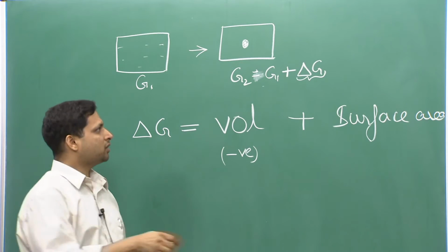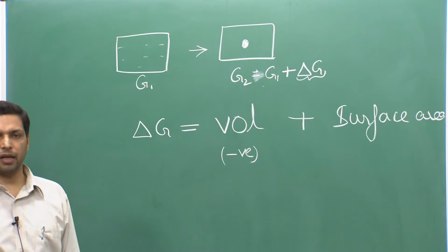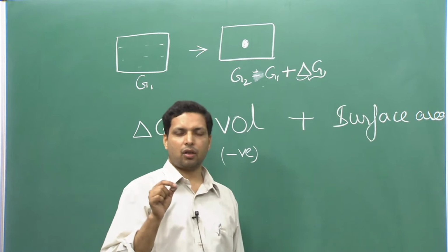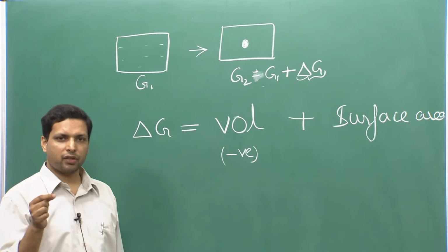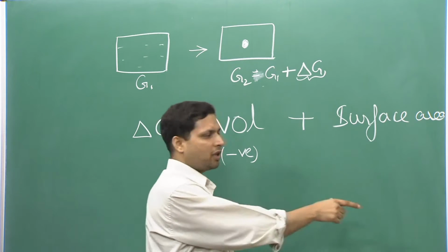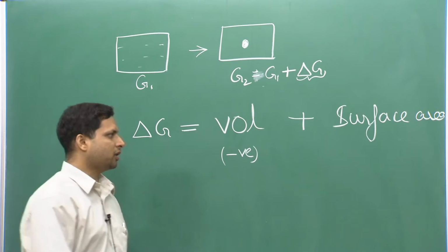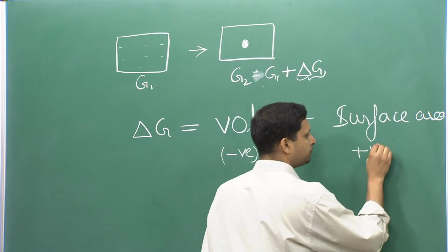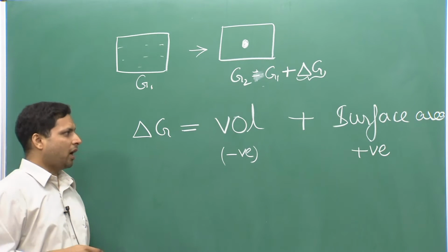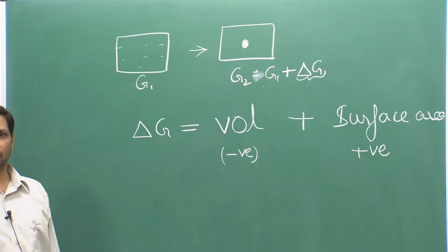However, when this solid has formed, a surface area has also been created. Surface always has some energy, so there is some surface energy related to it. Surface energy times surface area is the energy term we are talking about here. It is adding to the change in the free energy, so this is a positive term, increasing the overall energy.